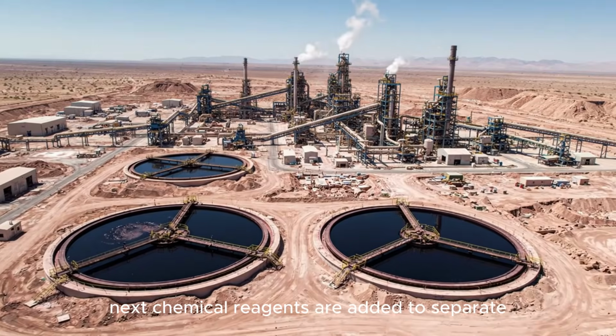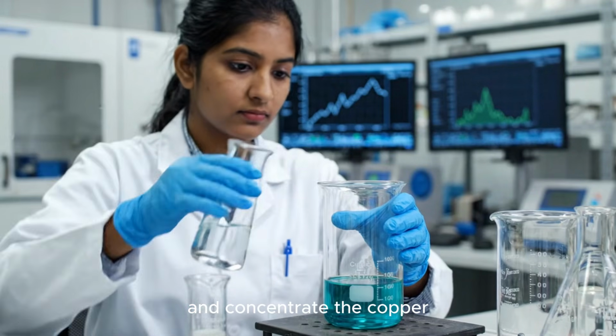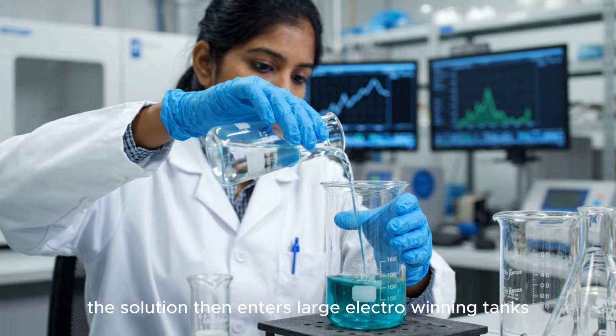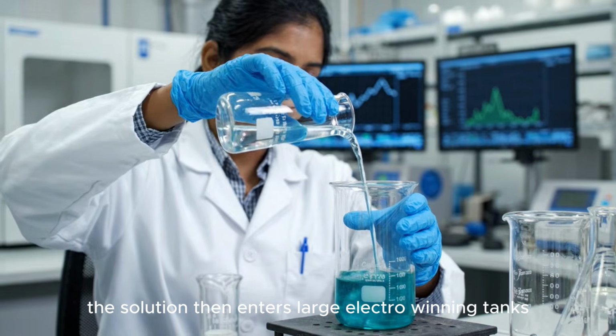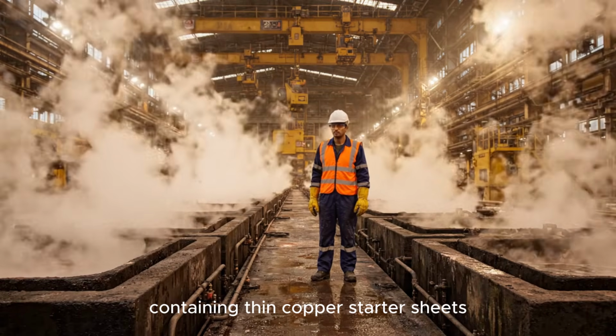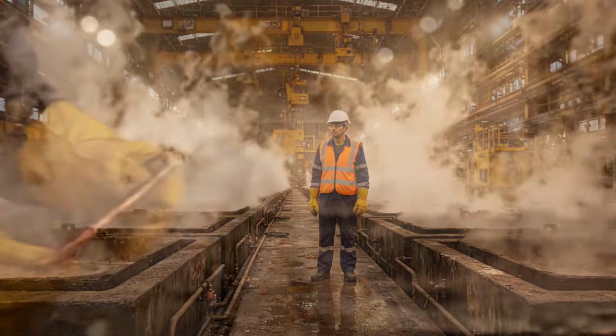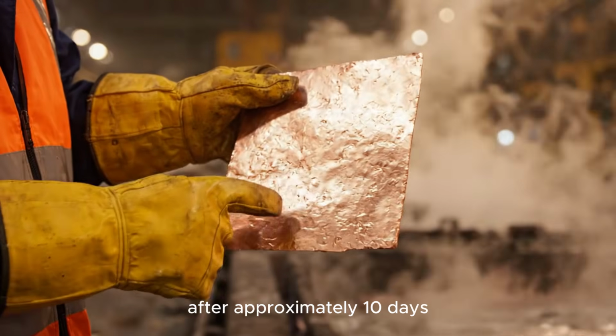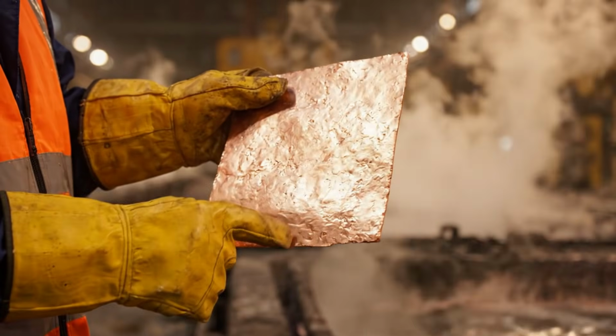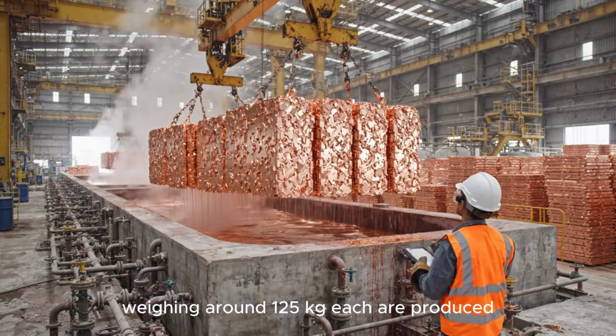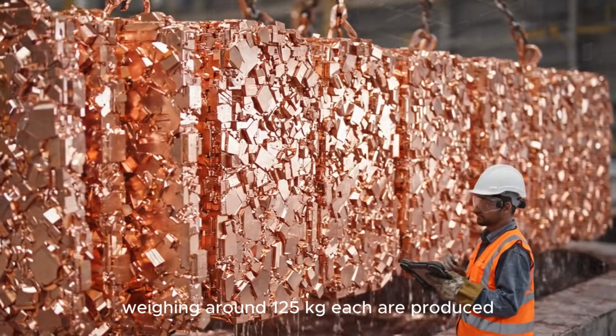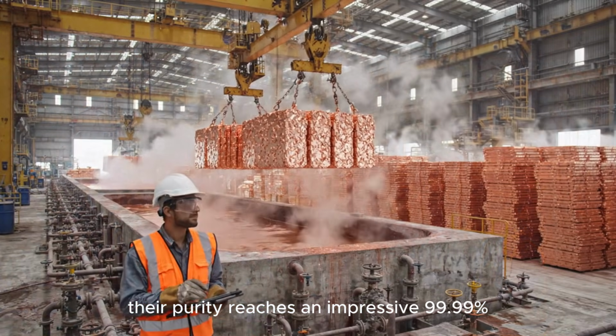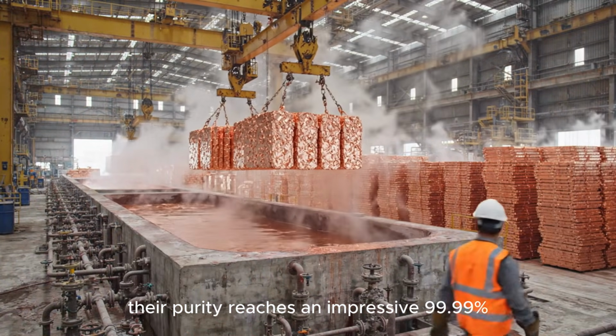Next, chemical reagents are added to separate and concentrate the copper. The solution then enters large electrowinning tanks, containing thin copper starter sheets called cathodes. After approximately 10 days, thick copper sheets weighing around 125 kilograms each are produced. Their purity reaches an impressive 99.99%.